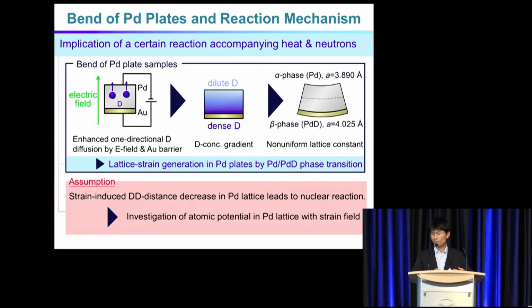And related to the phase transition, we wanted to investigate the strain induced because it bends, so some strain exists spontaneously inside. So a decrease in the atomic distance between the deuterium atoms in palladium is possible, and we calculated whether it happens under some strain.